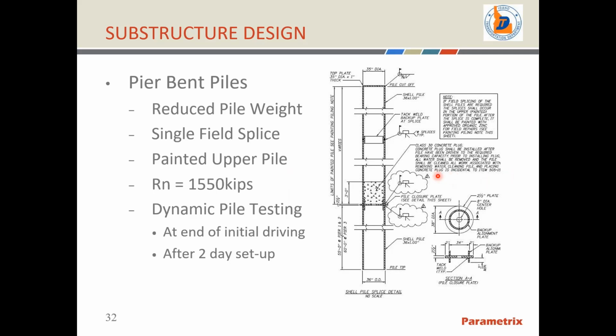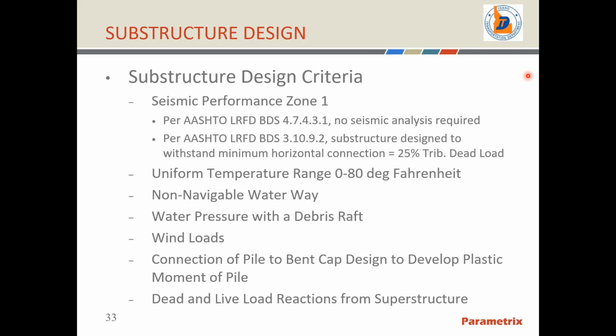In addition, there was only really one splice here, one weld to be performed, and that was at the closure plate. We did provide a detail for an optional splice if needed, but fortunately none of the piles needed to have a splice in this upper painted zone, so we still have good pile corrosion protection on the pile. So, substructure design criteria.